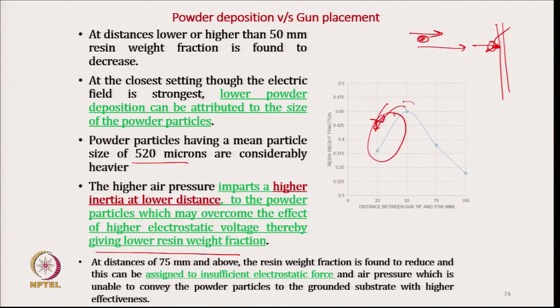But beyond a certain distance, like 50 mm, if we increase the distance, then the charging effect dominates. So, the lower charging will be dominating, which will ultimately affect the resin deposition. So, in this zone the reduction is due to the electric charge, and in the left zone the reduction is due to the inertia.